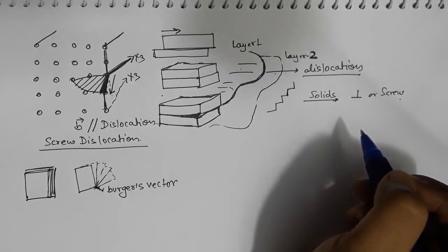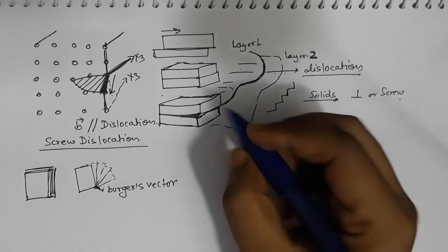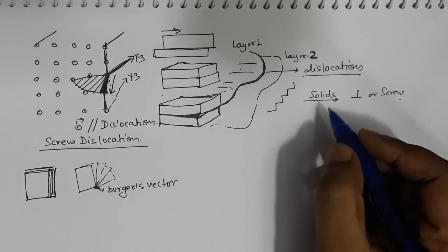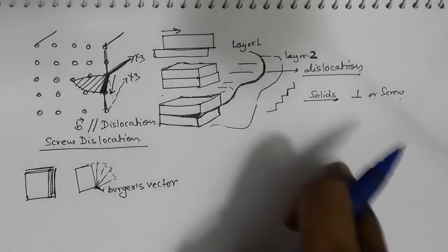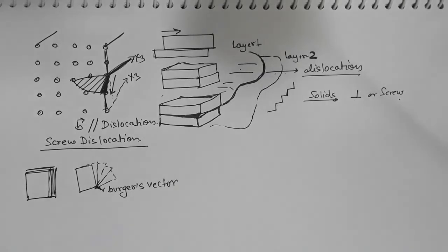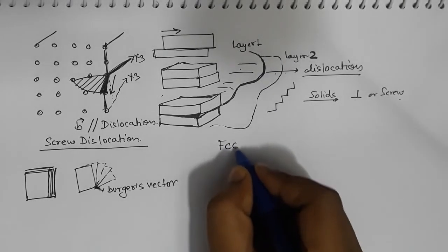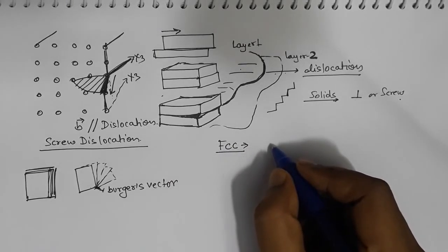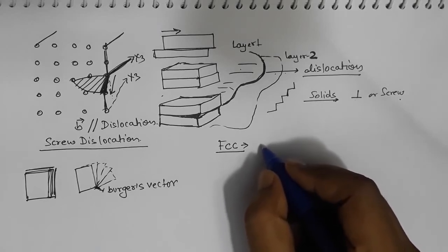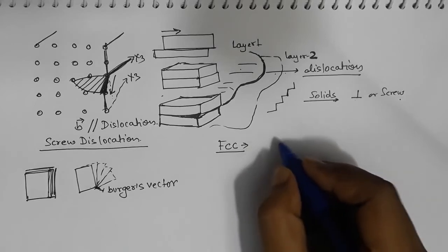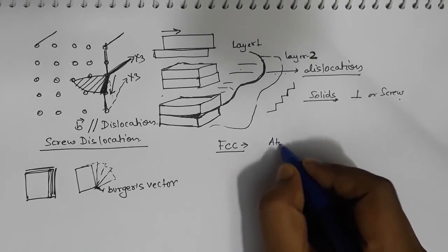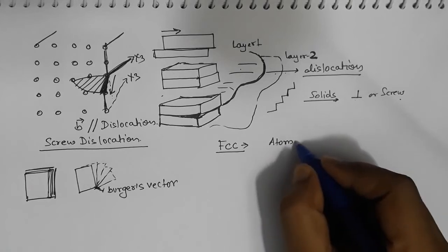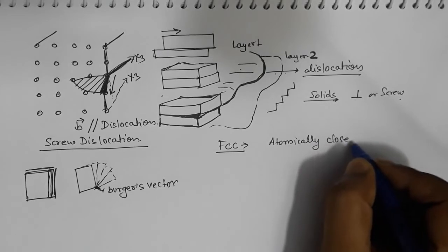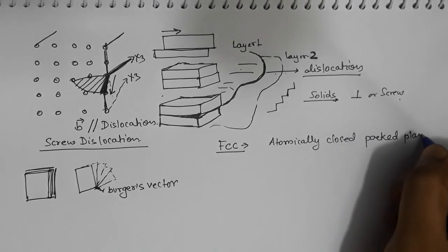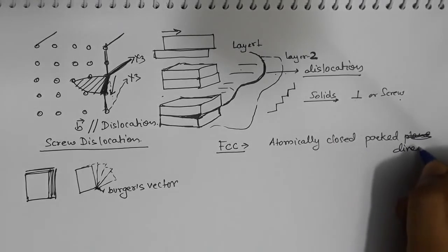So this is called a mixed dislocation, the dislocation in reality which looks like this. And one of the phenomena of this mixed dislocation is to move from one plane to another plane. So in FCC crystals, the direction on which the dislocation moves, the Burgers vector's direction, usually is the direction where the atoms are close to each other. The atomically close packed plane direction will be the direction in which it is easier for the dislocation to move.